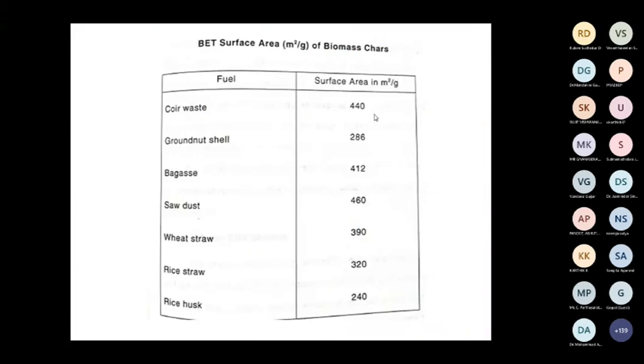This is the surface area of the char, you can see here. You can see the ground nut surface areas come down, because, as I told you, char preparation is at 900 degrees, and there is partial surface melting at 900 degrees. That is why the surface area of the groundnut char is a lower value. Whereas coir waste, bagasse, and sawdust have high surface area and a highly porous structure. These others are comparatively lesser in surface area.